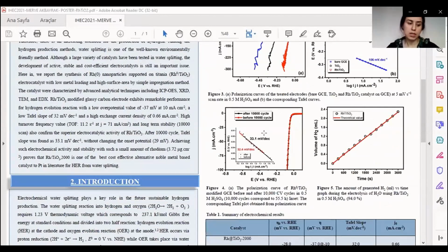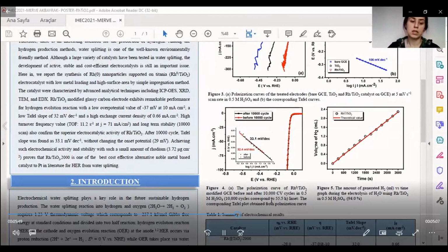The durability of rhodium titania was tested by applying 10,000 cyclic scans at a scan rate of 50 millivolt per second in sulfuric acid solution. The polarization curves obtained before and after the stability test indicate that there is a negligible change in the onset potential, overpotential, and Tafel slope. According to these results, one may conclude that rhodium titania is a highly durable electrocatalyst and provides superior electrocatalytic stability in hydrogen evolution reaction as compared to the rhodium catalysts in the literature.